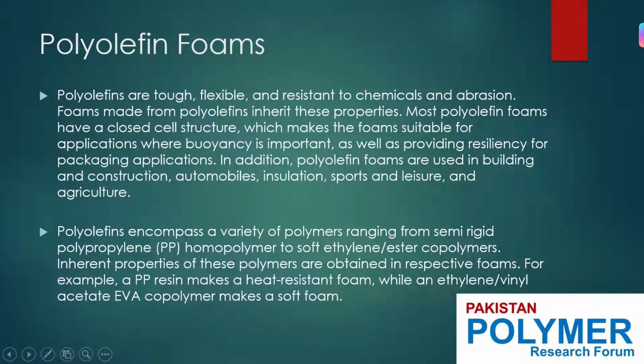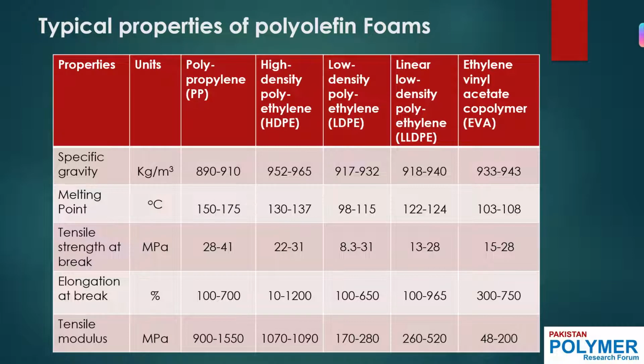If I talk about the polyolefin foams and the certain polymers that come under the banner of polyolefins, they include polypropylene, polyethylene, EVA, which is ethyl vinyl acetate. So based on the basic property of the polymer, we can get the same property in the end product also. Now I'm sharing the typical properties of polyolefin foams. You can have a look at the table. Here is a comparison between polypropylene, high density polyethylene, low density polyethylene, linear low density polyethylene, and ethyl vinyl acetate. Every polymer has a unique set of properties associated with it.